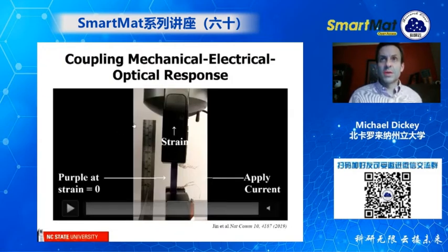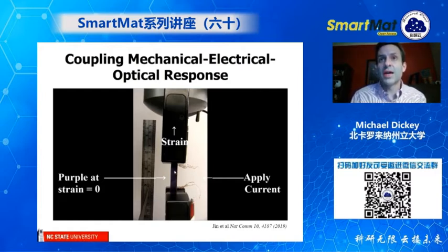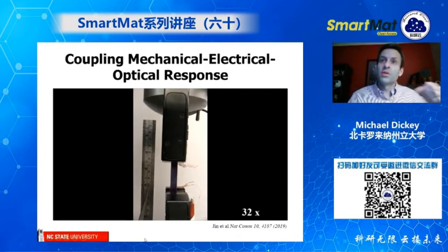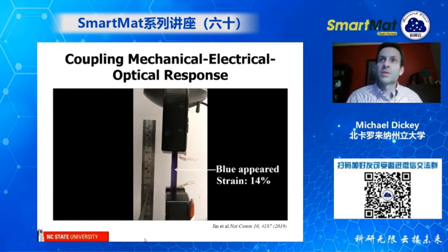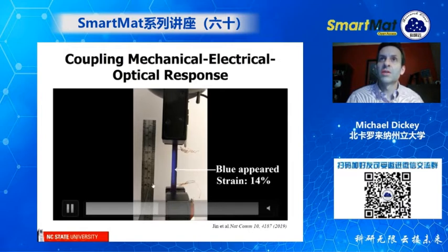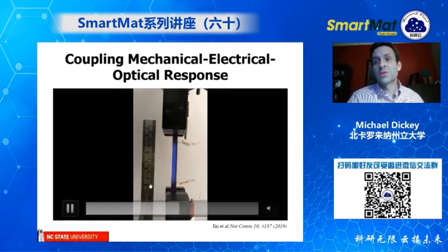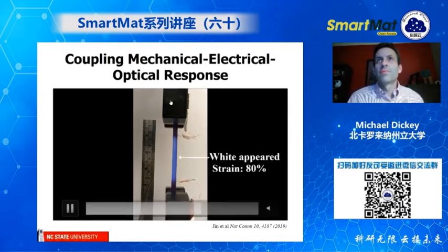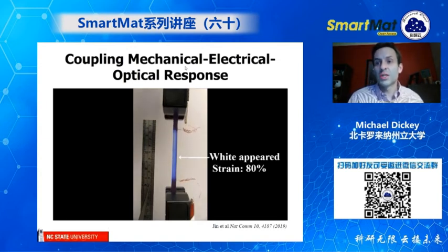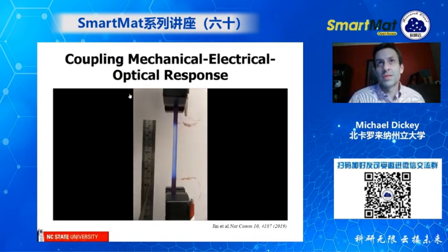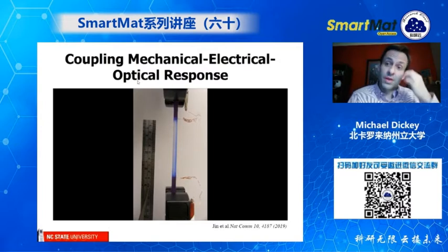So an illustration of this concept is here. This is a piece of silicone that has a liquid metal wire in it. And we're running electricity through here. So there's electricity, but there's no color change because the resistance is not high enough. But when you start stretching this wire, you make it longer and you make it narrower. And that changes the resistance. So then you start to see a color change due to joule heating. So this is interesting because you have a responsive material that couples mechanical properties, so stretching, electrical properties, which is resistance, and optical response, which is color.